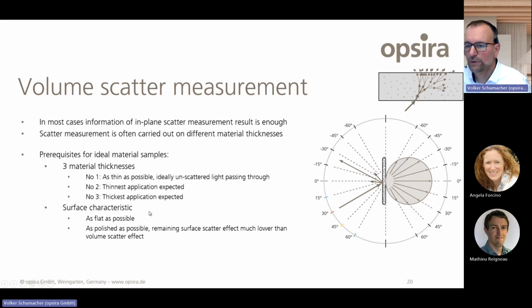For the surface characteristic, it's very important that the surfaces are flat and polished, because we only want to see the effect of the volume scatter characteristic, and we don't want to see the effect of the surface scatter characteristic. So it should be a polished surface so that the only scatter effect will be created from the volume.